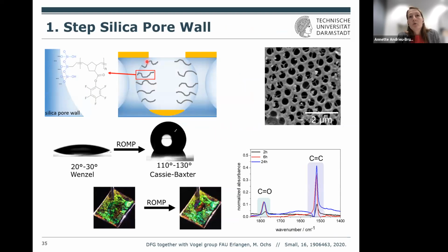So the first step was to use silane chemistry that then functionalized the silica pore wall in a pore wetted state. And then we added a ROMP polymer that is quite hydrophobic. So again, that increases the de-wetting state of water in these pores. And the first step, then you can see already in electron microscopy that obviously there's polymer inside. The wetability, the contact angle increases drastically. So this as well indicates that functionalization worked out.